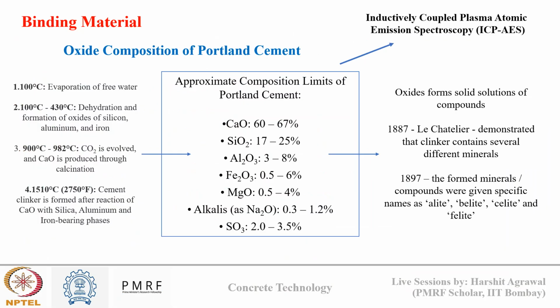Now, to understand the chemistry behind what we obtain from this kiln phase, which we call clinker, we need to understand the oxide and the compound composition of Portland cement. After passing through the kiln phase, limestone and clay, upon exposure to higher temperature, form different oxides of calcium, silica, and aluminium. Limestone is the source for calcium, and clay is the source for silica and aluminium. Along with this, we also add some iron impurities in the initial raw mixing, which is the source for iron oxide. So limestone, clay, and impurities, upon exposure to high temperature, convert into different oxides of calcium, silica, aluminium, and iron after liberating CO2 and water.